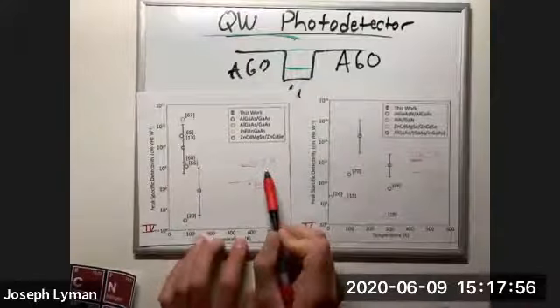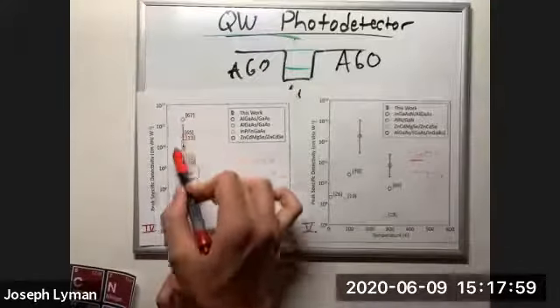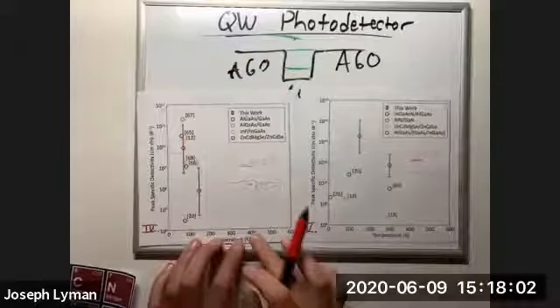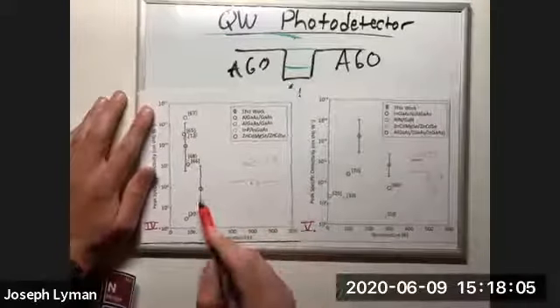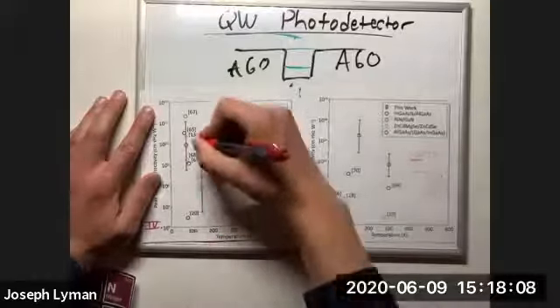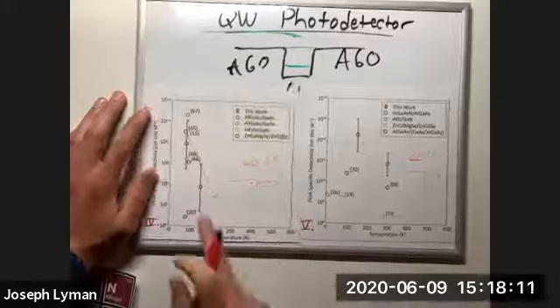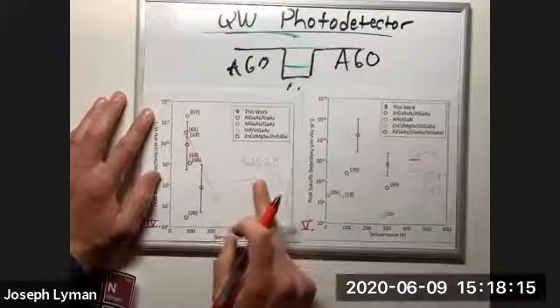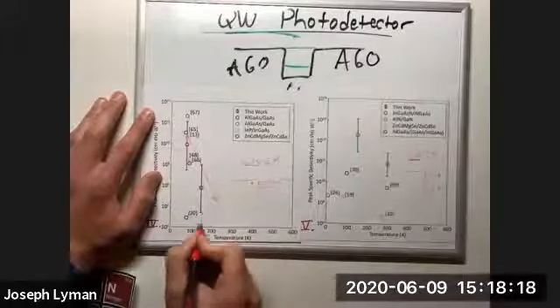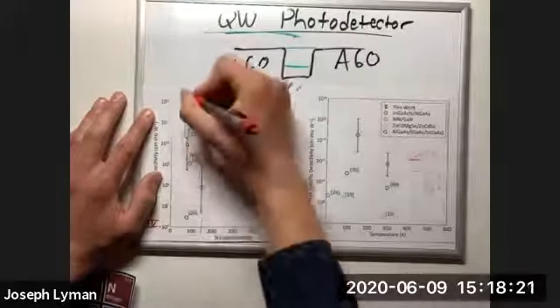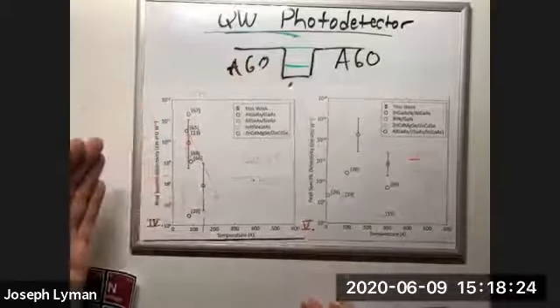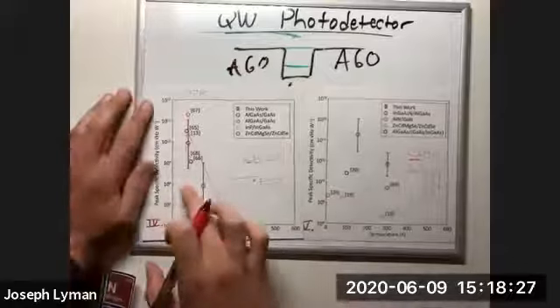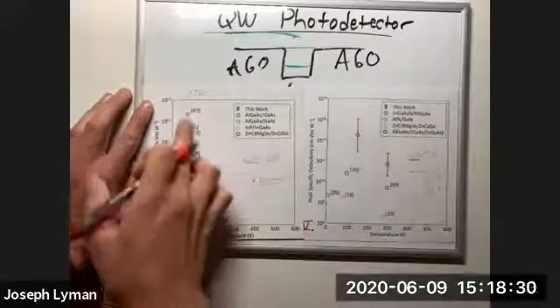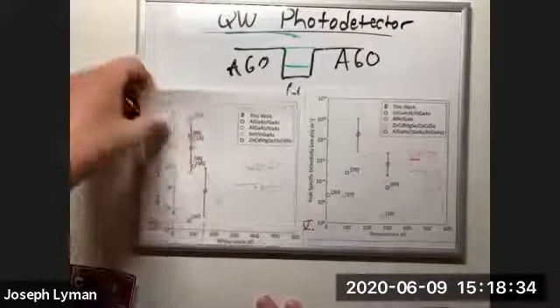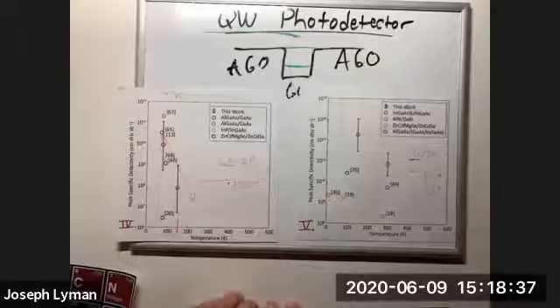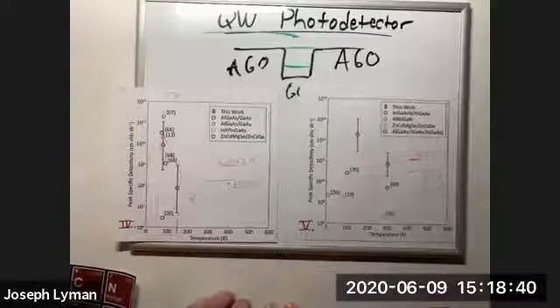For the long wavelength detector, we show comparable performance to what's been done before. It's not predicted to be significantly better, and what's more, as the temperature increases, the detectivity tanks. That's why typically these long wavelength quantum well photodetectors have to be operated at low temperatures. Right here, these temperatures are at 77 Kelvin, which is the temperature of liquid nitrogen. So they must be cooled with liquid nitrogen to produce reasonable detectivities, which sounds like a pain and a burden, and it is, but that's typically what has to be done in infrared cameras using this technology.